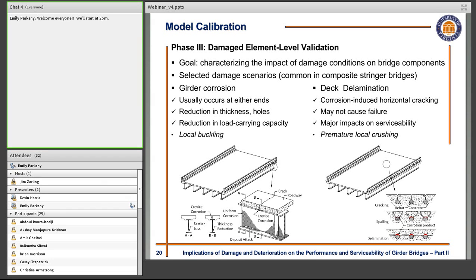In the other case, deck delamination or any other sources of deterioration associated with the reinforced concrete slabs, we may have delamination as a result of freeze-thaw cycles or corrosion-induced delamination. In the case of corrosion-induced delamination, we have these horizontal three-dimensional planar cracking that is parallel and close to the exterior surface of the reinforced concrete deck. And as opposed to girder corrosion, this may not cause the structure to fail or reduce the capacity, but we may have some impacts on the serviceability because of this type of damage as a result of premature local crushing failures of the top surface of the concrete deck.